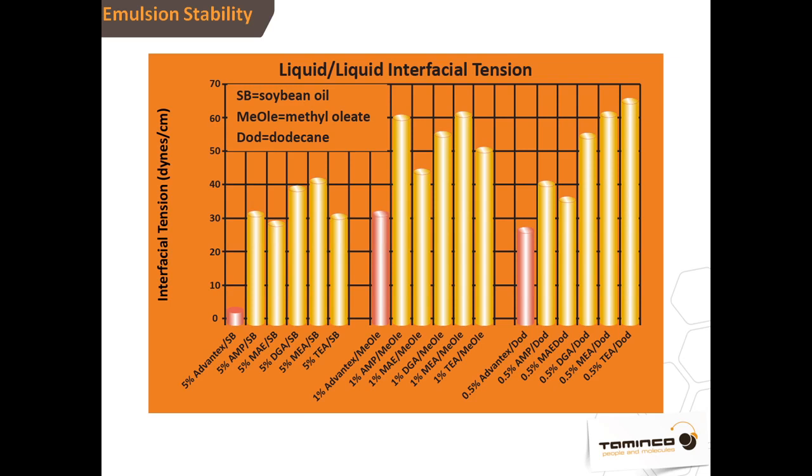And we arrayed these alkanolamines from HLB 20, less functional, very hydrophilic alkanolamines, all the way up to higher molecular weight, more structurally elaborate alkanolamines. The effect is certainly more noticeable as you go to higher concentrations. And at 5% alkanolamine in water, you see some pretty significant differences in liquid-liquid interfacial tensions as you go to these mid-range HLB, more multifunctional alkanolamines. And we think that this type of an effect is a good explanation for many of the colloid stabilizing benefits of certain alkanolamines. Pigment dispersant enhancement, emulsion stability enhancement, and other things.